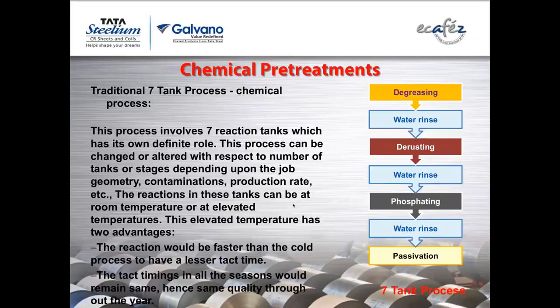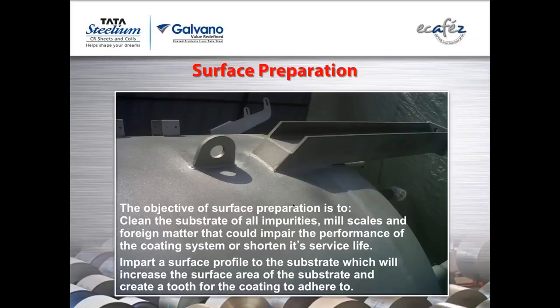After passivation, if the water lingers on the job, you are going to have a rusty feel or a flash rust, what we call. So you have to have a water drying oven if possible. If not, another idea is to heat up the passivation chemicals or that bath. So the job will pick up the heat. Once it comes out, immediately air blow the job so it is free of water. So either way, you can solve these problems.